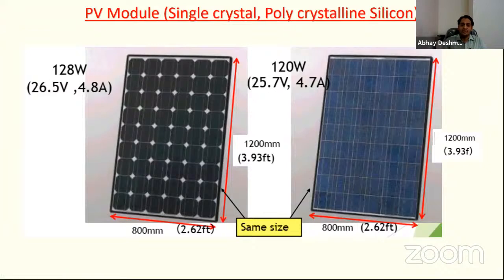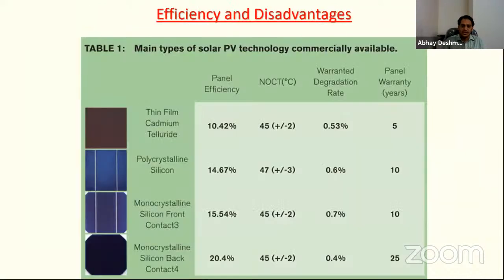Now it depends on what application or where we want to install these models. Okay, and then if you compare the efficiencies as well as the warranty of your silicon. So if you take a thin film cadmium telluride, you have a panel efficiency of 10.42%, and you have a temperature of 45 degrees ±2. You can play around. Then warranty degradation is 0.53%, and panel warranty is 5 years.